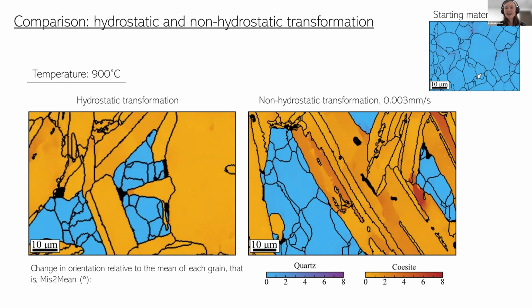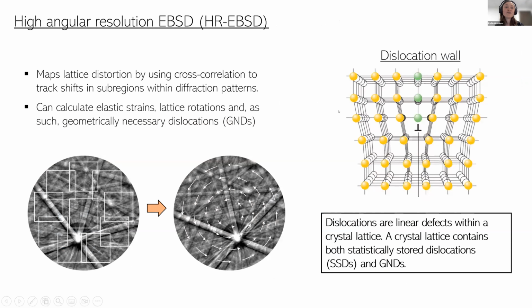And so in doing this, we're going to look at EBSD, but taking it a little bit further by doing something called high angular resolution EBSD. What this does is, whilst you're collecting EBSD data, you save all of the diffraction patterns, which are shown here. And then for each grain, you take a reference diffraction pattern, and you choose a number of regions of interest, which you can see here with the white squares. For each of these regions of interest, you correlate for every diffraction pattern in the grain, you work out the displacement gradient tensor, or the strain tensor, of each of these squares comparative to the reference one. That was not very well explained, but it gives you an idea basically of the elastic strains, which give you an idea of the internal stresses.